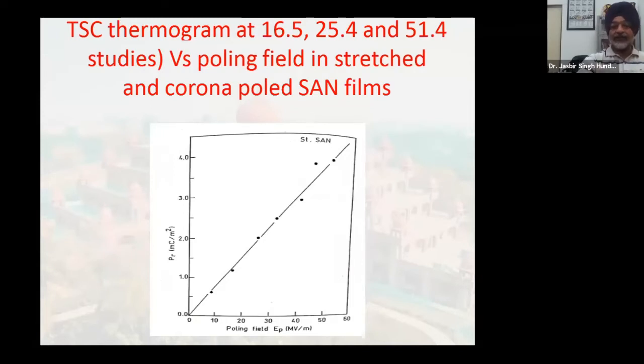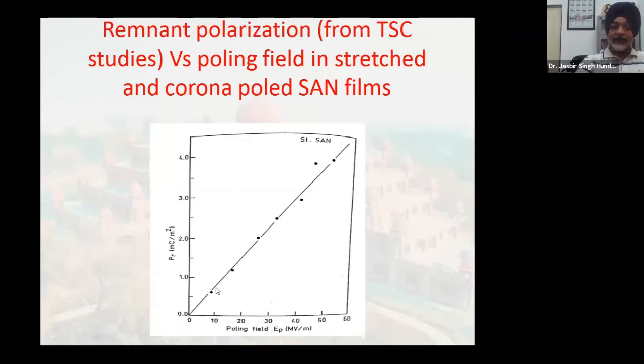Okay, from TSC we were able to calculate Pr, that is polarization, and it was found that this polarization varied completely linearly with the poling field. Look here, right? So this linear dependence of polarization on the poling field corroborates that whatever piezoelectricity, pyroelectricity or ferroelectricity we are having in corona poled films is mainly, in fact only, due to dipolar polarization, not ionic or electronic or space charge polarization. So it is due to dipolar. The essential feature of dipolar polarization is that polarization has to be proportional to the poling field.